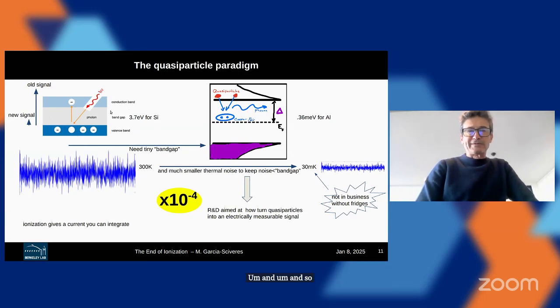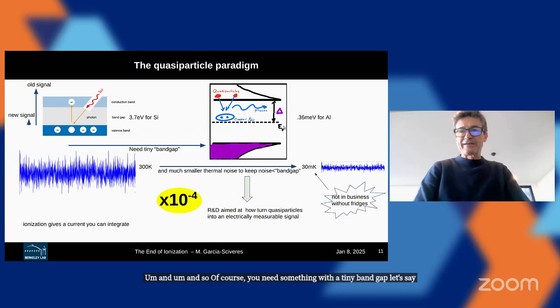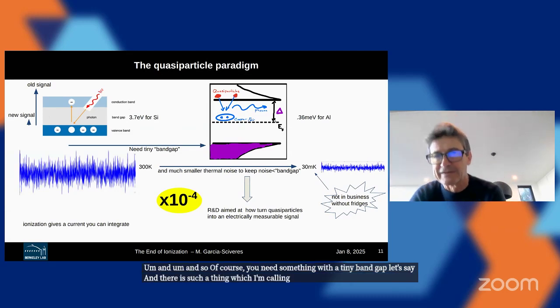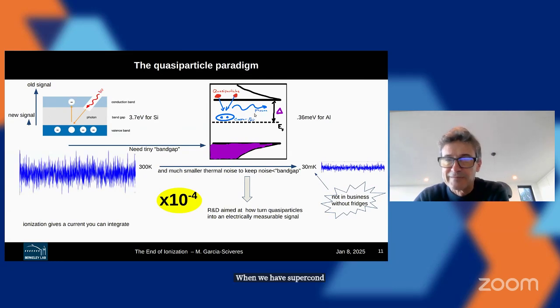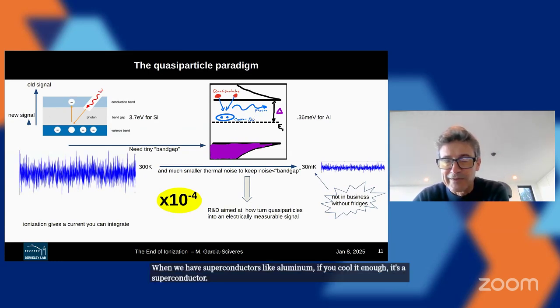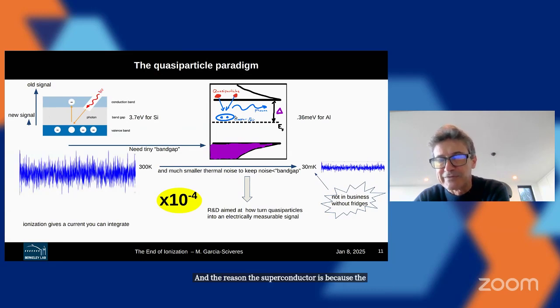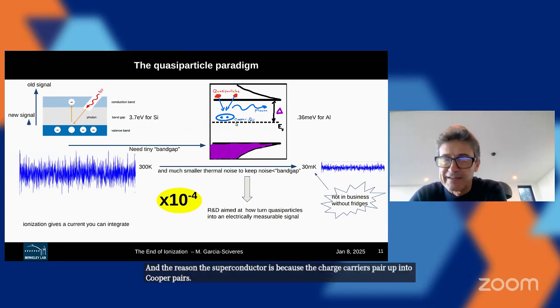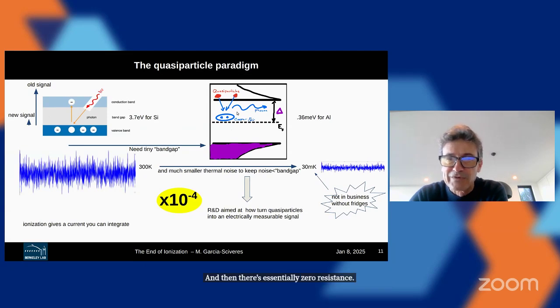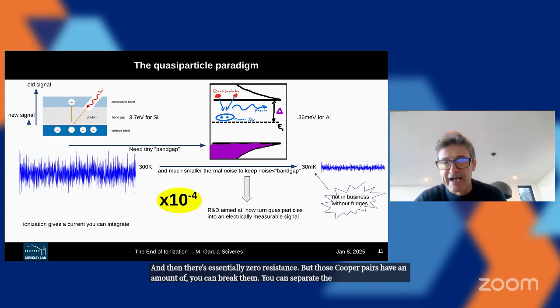And so of course you need something with a tiny band gap, let's say, and there is such a thing, which I'm calling band gap impedances here. When we have superconductors like aluminum, if you cool it enough, it's a superconductor. And the reason is because the charge carriers pair up into Cooper pairs. And then there's essentially zero resistance. But those Cooper pairs can be broken. You can separate the charge carriers out of Cooper pairs by hitting a Cooper pair with a certain amount of energy. And that energy to break Cooper pairs is 0.36 milli eV for aluminum. So that's an interesting factor of 10 to the 4.